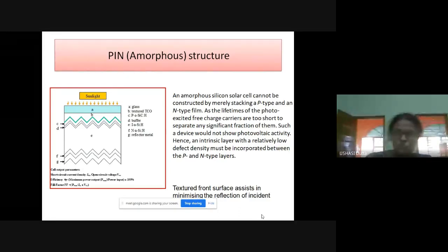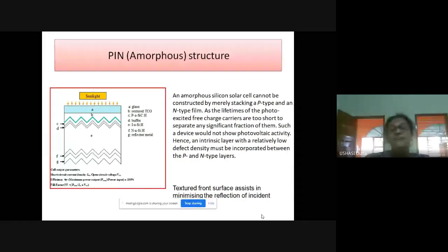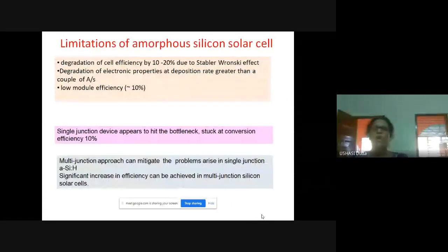Such a device would not show any photovoltaic activity, hence an intrinsic layer is incorporated between P and N type. And here we see the textured front surface, which assists in minimizing the reflection of the incident light. But there are some limitations of amorphous silicon solar cells. Actually, this amorphous silicon degrades its efficiency due to prolonged light exposure, and its module efficiency is also very low, and it